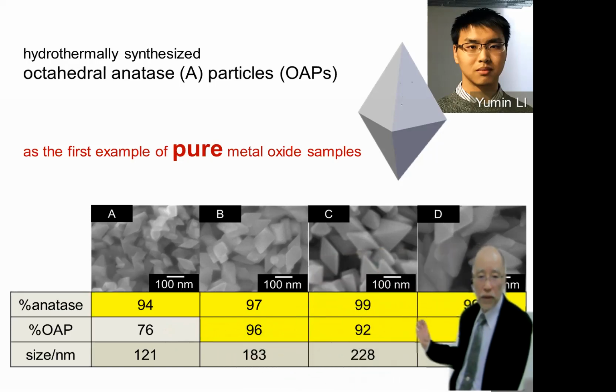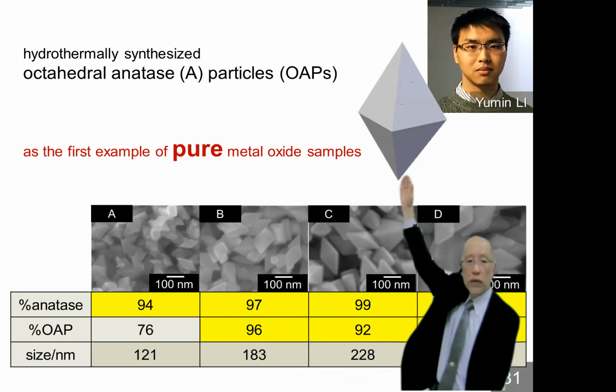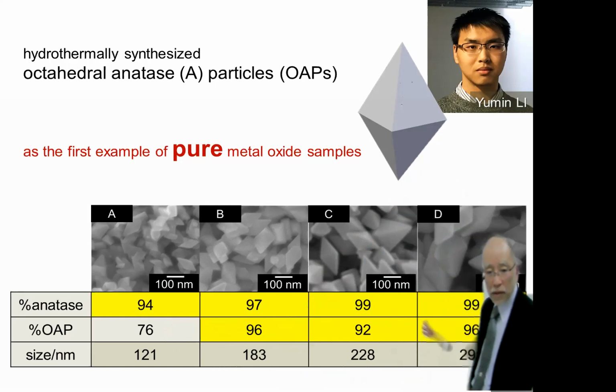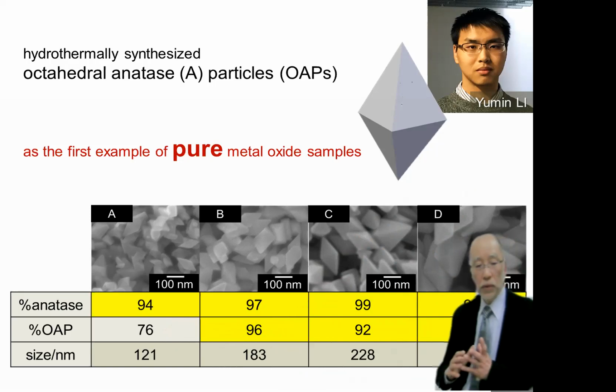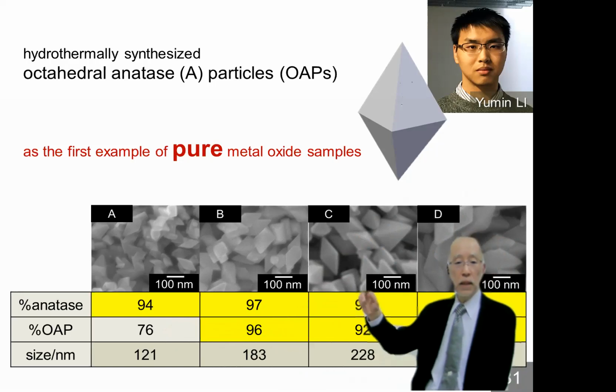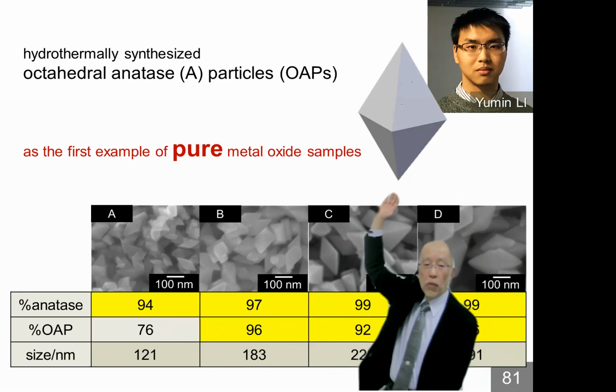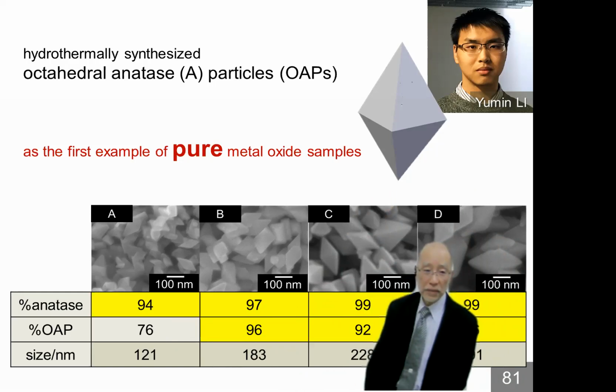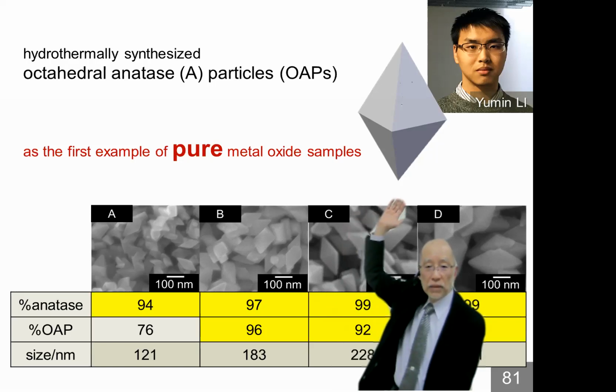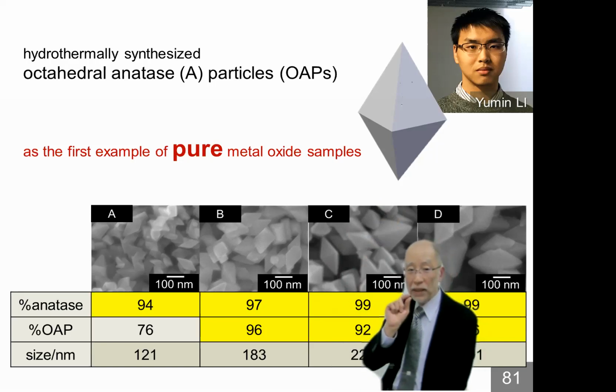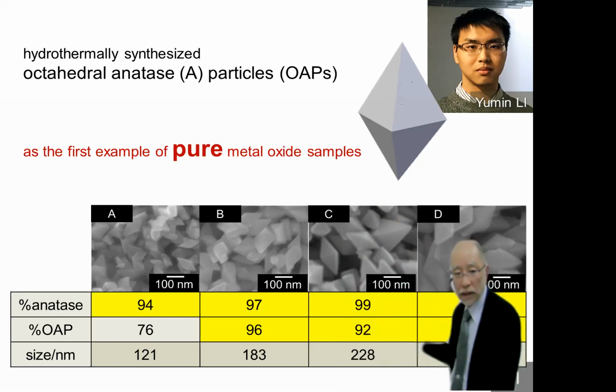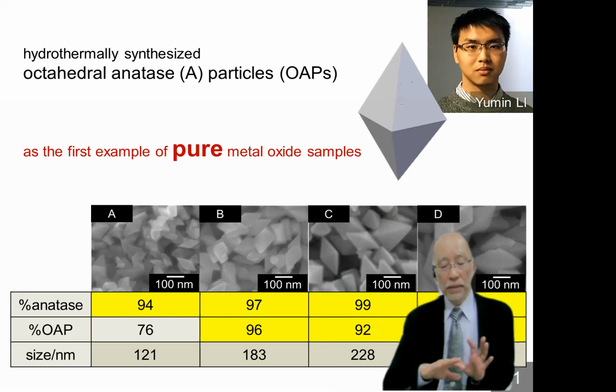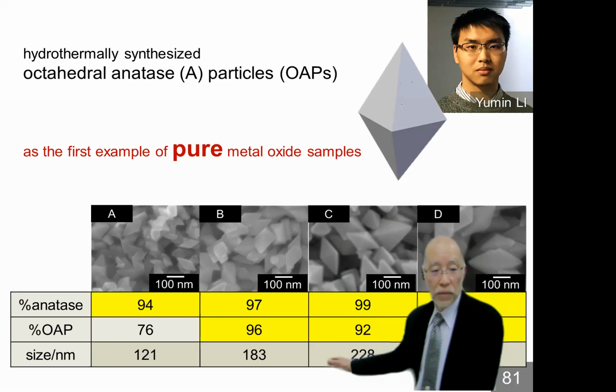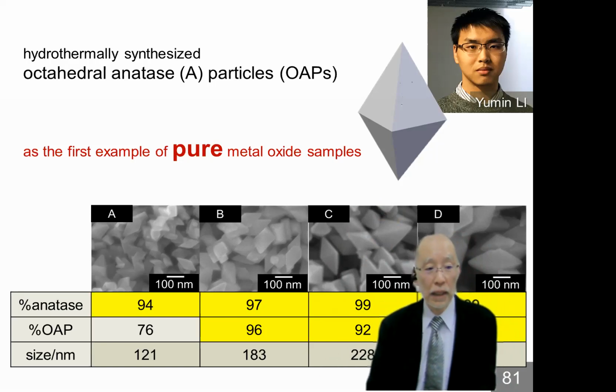And the size in nanometer is determined by measuring the size from bottom to top, and the average is calculated like this. And it is possible to calculate the density or weight of one octahedral particle. And also we can calculate the surface area of one particle of the size shown here. And actually, the measured specific surface area is almost the same as this value calculated from the size. So that means the purity is very high.